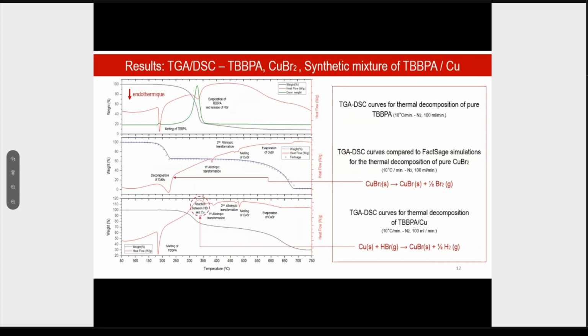And then we compare this behavior, and we are going to study experimentally, first the decomposition of tetrabromobisphenol A, as you can see in the first slide. Tetrabromobisphenol A, which is the flame retardant that we are discussing, starts to melt at a lower temperature, about 180 degrees, and then starts to evaporate at about 300 degrees. The evaporation of tetrabromobisphenol A also releases the hydrogen bromide that we mentioned earlier.